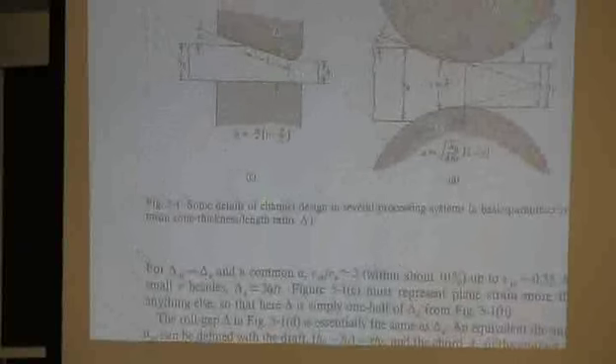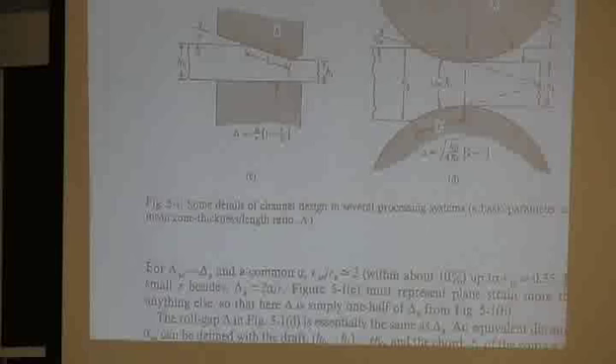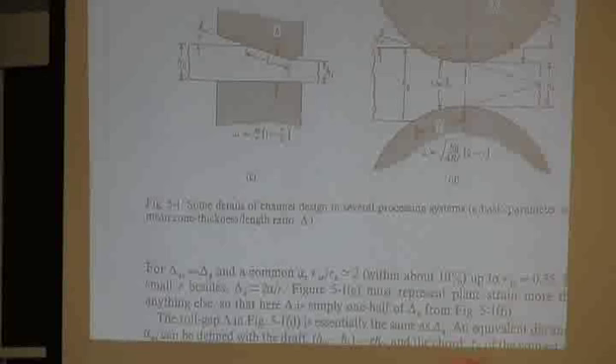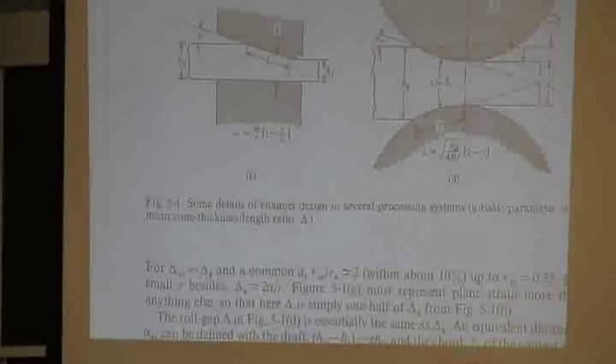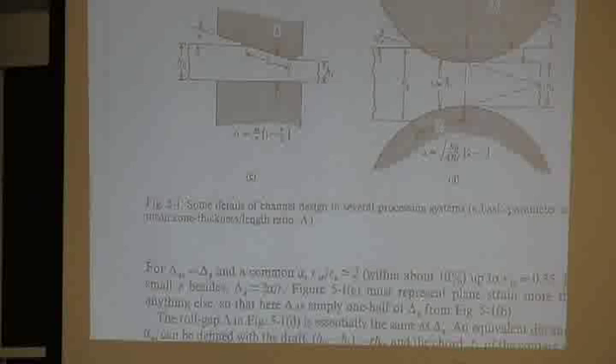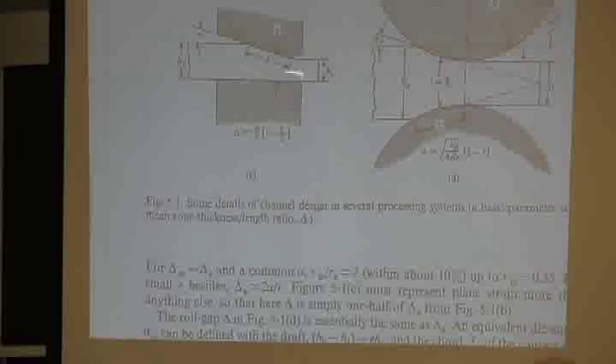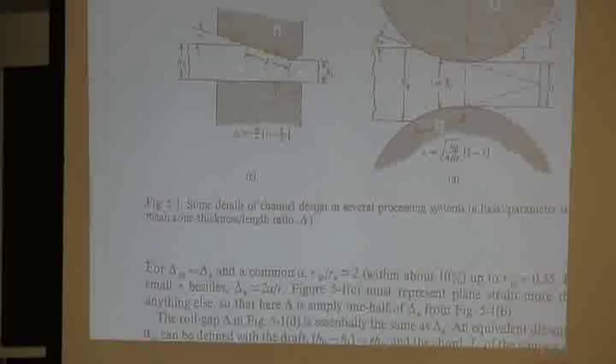If you do something like thinning of the wall of a tube, it's one of the most important deformation processes that we use. Anybody know what we use it for? Ever seen a beer can? They make a beer can by what they call ironing the wall. They have the term ironing because it's just like taking an iron, or rolling out pizza dough from one direction with a rolling pin, and you just push everything until it's thinner. So here's rolling out a pizza dough, or ironing of a beer can or a Coke can.